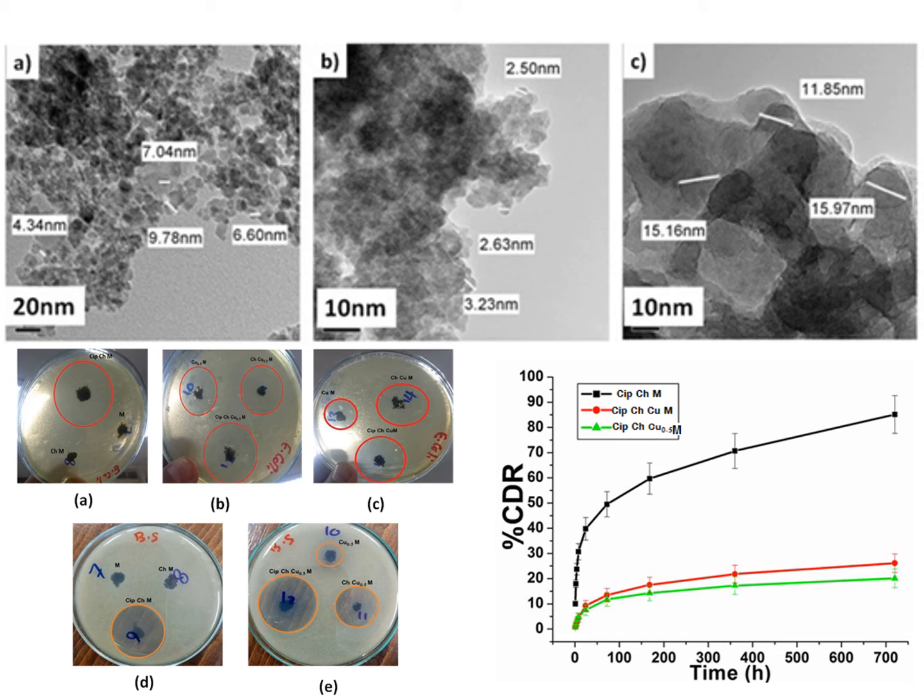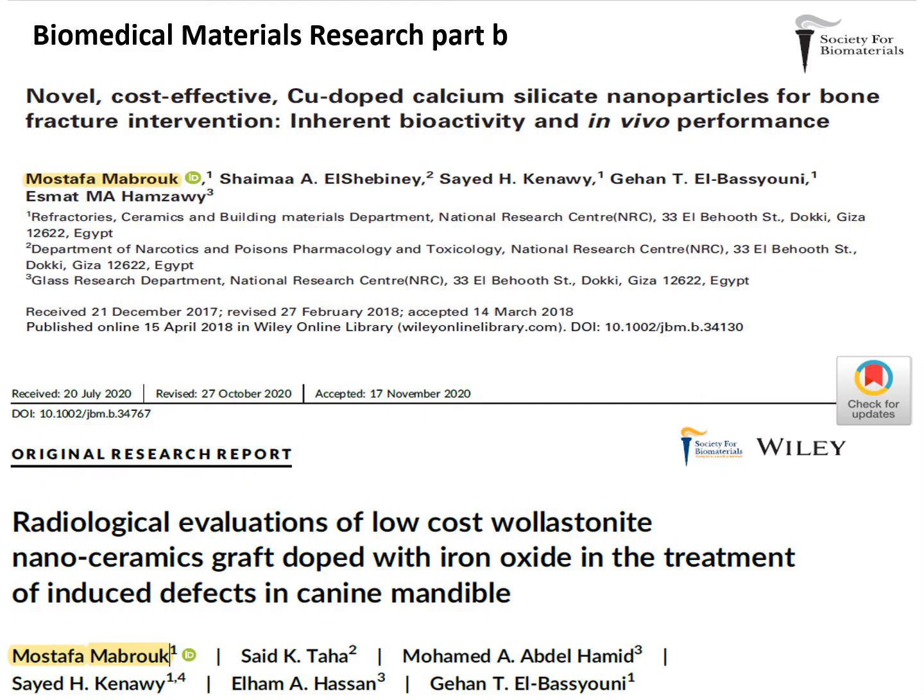We find that partial substitution is giving the finest nanoparticles, compared with complete substitution with copper. Also, we confirmed the antibacterial effect of these nanoparticles using the agar well diffusion technique as an antibacterial test, and this is the drug release of these nanoparticles, ciprofloxacin drug release, and we found that the presence of copper is down regulating the drug release from these multifunctional particles.